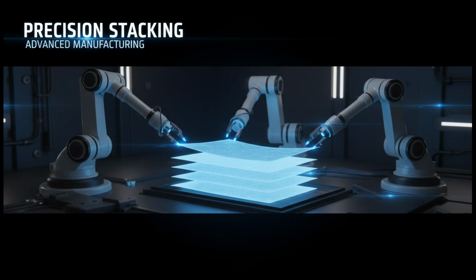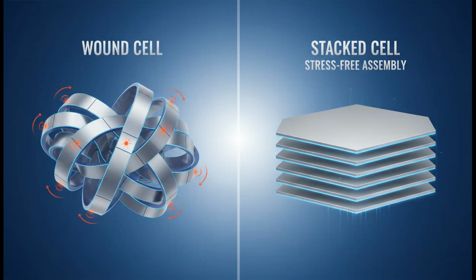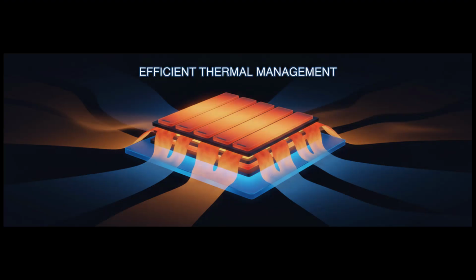Manufacturing these cells is the next big challenge. Ganfeng is using a high-precision stacking process rather than the traditional winding method used for liquid cells. Winding a battery like a jelly roll creates stress at the corners. Stacking them like a deck of cards ensures that the zero-strain anode stays perfectly flat and functional. This stacking method also allows for better cooling. Heat can be drawn away from the flat surfaces much more efficiently, allowing the battery to maintain peak performance even under heavy loads.